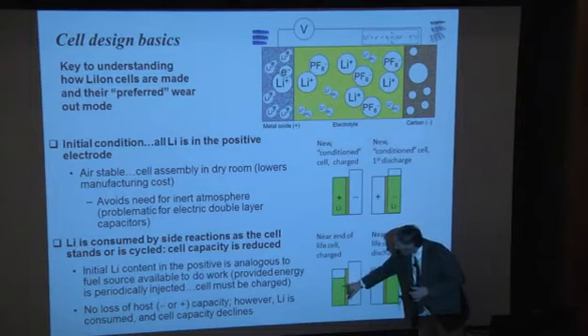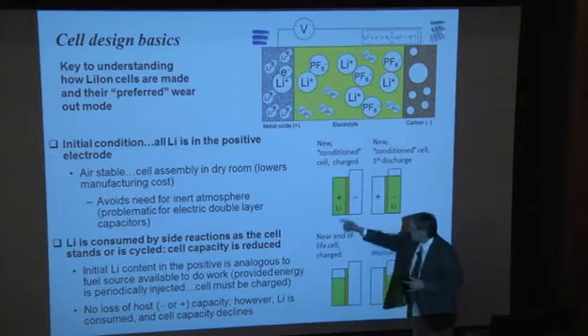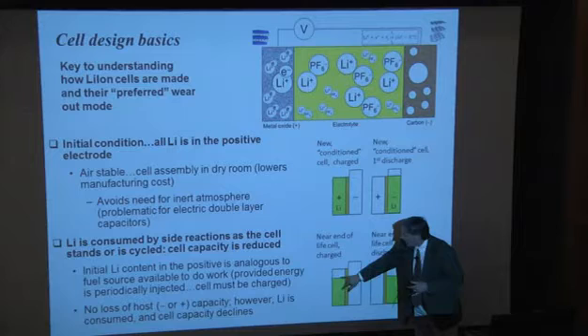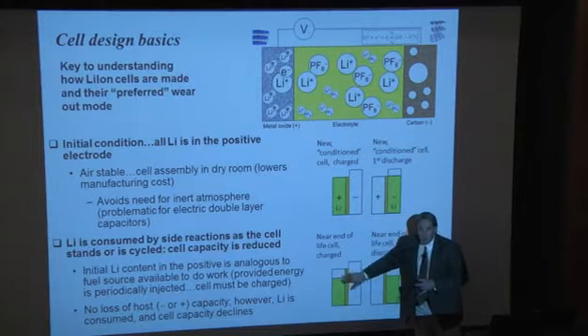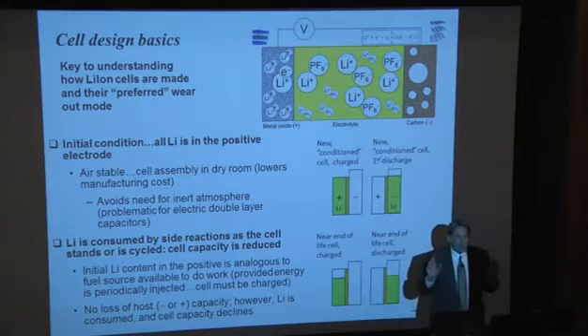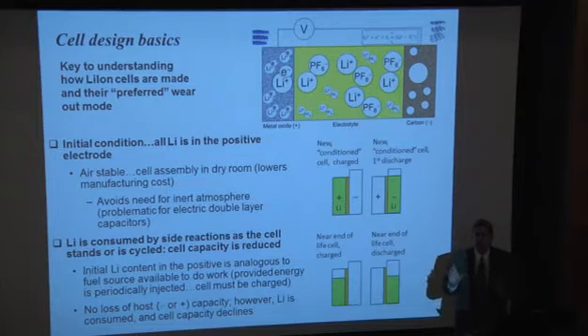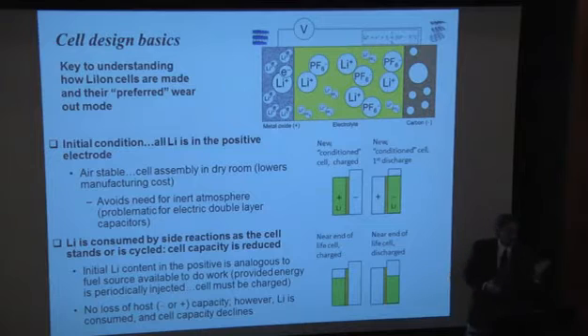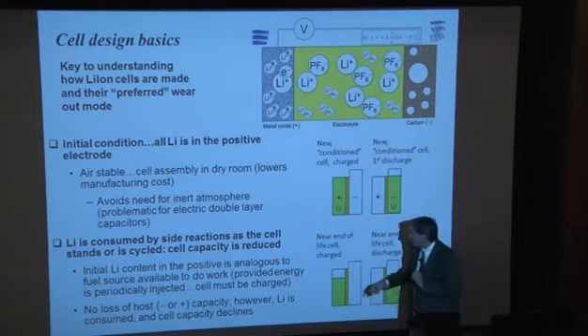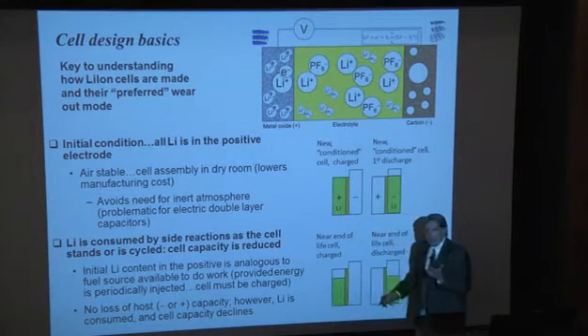The lithium content in the positive electrode, when you're fully charged, is such that you've left over some material. What we find, and this is why I call it the preferred wear-out mechanism, is the host materials have not lost any sites. They're still available. If you take the cell out and cycle in a separate half cell, you find out that host material could cycle lithium just as it did initially. What's happened is you've consumed lithium in the cell. And that's where the life modeling comes in, which I'll talk about.